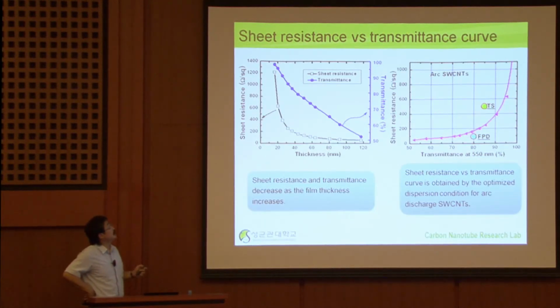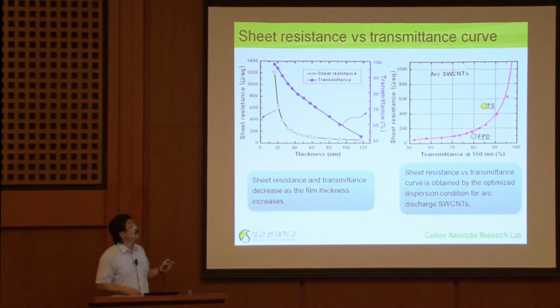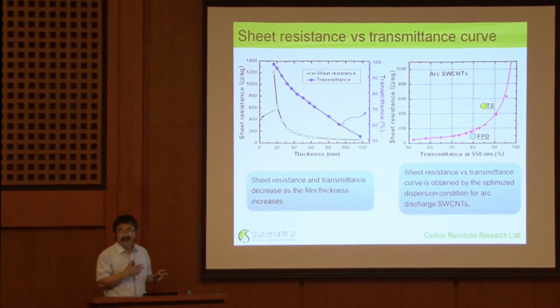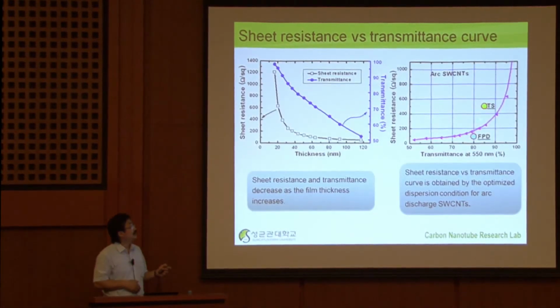Okay, if you increase the thickness, of course, the resistance decreases. But if you increase the thickness, of course, the transmittance of the film decreases as well. So these two are the trade-off, sort of. So you can also plot this in terms of transmittance and sheet resistance. We always have this curve. Okay. So for instance, for touch panel application, we need 90% transmittance, and the resistance should be like 100 ohm per square. But still, these carbon nanotubes cannot meet this criteria.